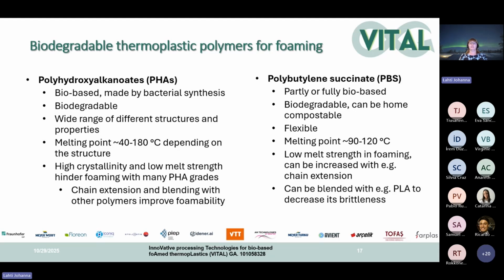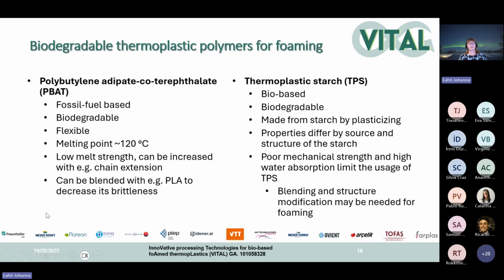Then one other interesting polymer, PBS, polybutylene succinate. It can be partly bio-based, or there are also grades that are fully bio-based. Then it is biodegradable. There are also home compostable grades available. And also with this polymer, low melt strength is sometimes a challenge, and we can try to affect that to get it foamable. Or we can use blending, for example, with PLA. Then I think this is my last slide of these polymers. Two more to mention. PBAT, polybutylene adipate terephthalate, which is fossil fuel based, but it is a biodegradable, flexible polymer. Once again, low melt strength has been mentioned as a little bit negative thing here.